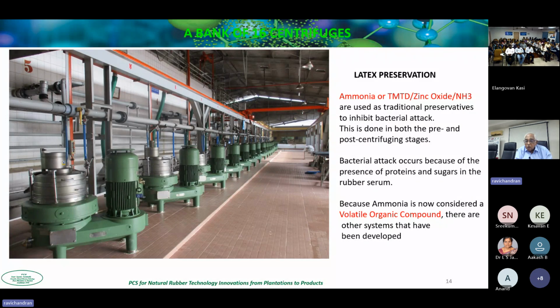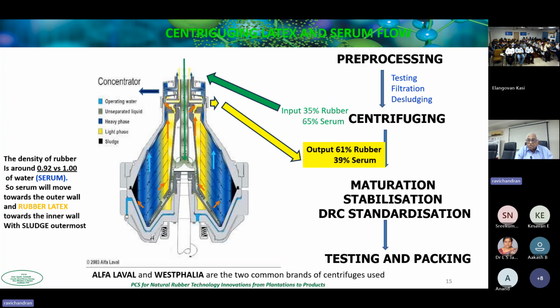Because ammonia is now considered a volatile organic compound, there are other systems that have been developed and put into place. This is the typical centrifuge that we take the field latex. There's a pre-processing, which involves testing of the latex, filtration to remove any coagulum, desludging to remove magnesium. The magnesium in the latex varies according to the season, and it will be low most of the year, but around the defoliation season, the magnesium goes very high because the leaves are not removing it. So we have to remove the magnesium by using diammonium hydrogen phosphate. Then the desludged latex goes to the centrifuge.